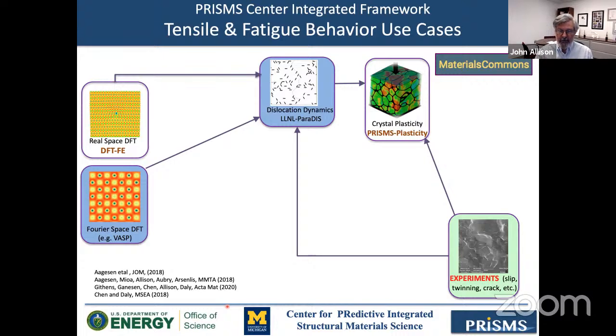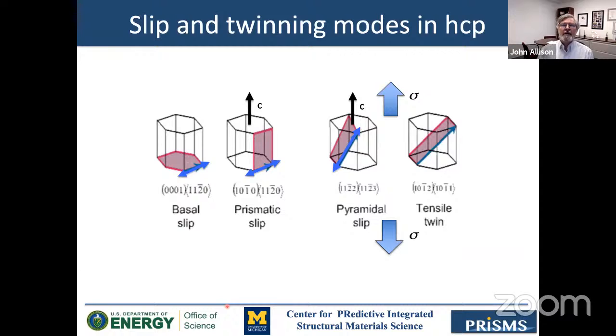What I will talk about, in a similar vein, is that we've been looking at fatigue behavior. And one of the things I want to talk about in this use case is cyclic twinning and detwinning during fatigue loading. So to set the stage for this, I need to remind you of some of the complexity of magnesium. It's hexagonal close packed. And of course, as I mentioned earlier, we have deformation modes. The primary deformation mode is basal slip on the basal plane, with a 11-20 slip direction. We can also have prismatic slip, which is a little bit more difficult, and pyramidal slip to get along the C-axis, which is a lot more difficult in many magnesium alloys. And then, of course, in HCP materials, twinning is a very, very important deformation mode as well, which adds to the fun.